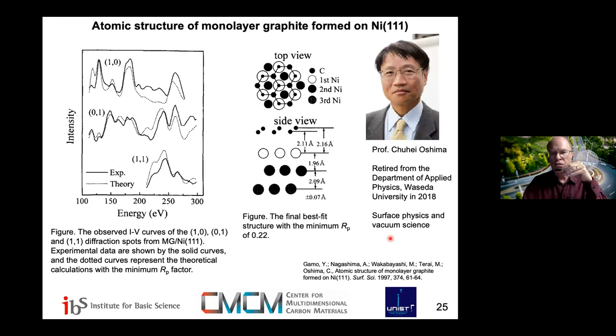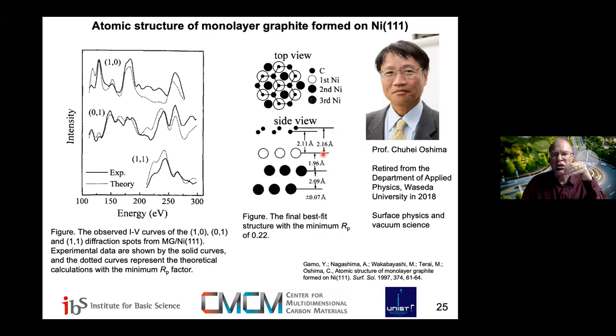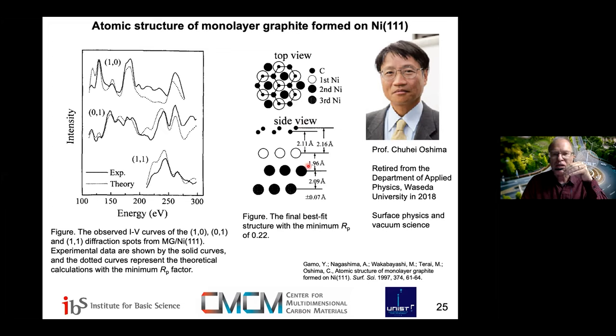Oshima in Japan had a number of very beautiful studies of quote 'monolayer graphite' — what we would now call graphene — and really delved into structure. Through their studies, they were able to understand that on nickel, such as nickel 111, we have a different situation than on some other materials like copper. This is referred to as chemisorption, though I think it's still an exciting question of whether covalent bonds are actually forming between the nickel and graphene. The interlayer separation is significantly different than on copper or platinum, where it is of the order of about 3.3 to 3.4 angstroms.